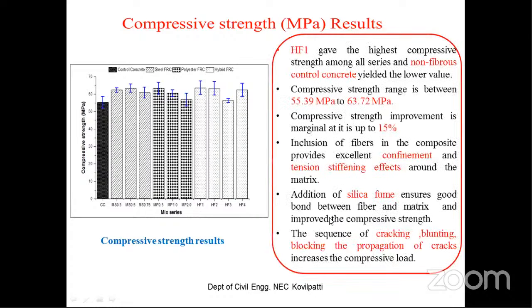So what we can conclude is fibers will improve the compressive strength, though in single FRC or hybrid FRC the improvement is very marginal, and it is observed only up to 15%. The confinement of the fiber and the tension stiffening effects of the fiber will improve the compressive strength. And also I have added silica fume 5%, so that will also enhance the bond between the fiber matrix and the concrete. That will always provide a dense microstructure. So all these parameters have influenced the compressive strength, but not a very big change is expected, only 15%.